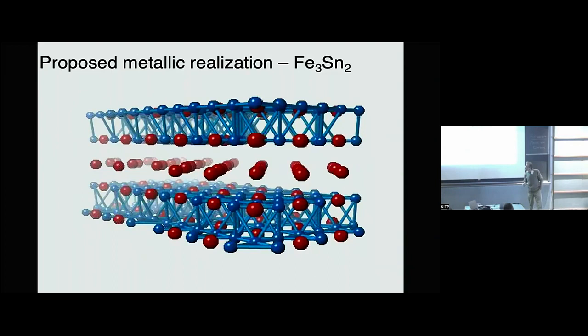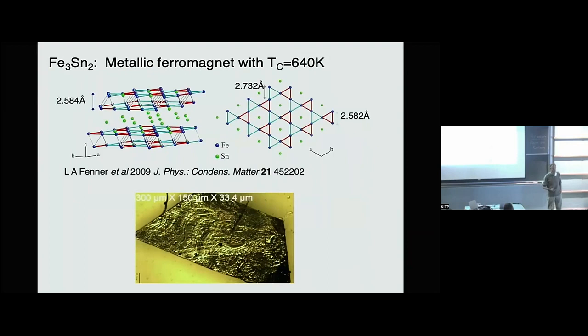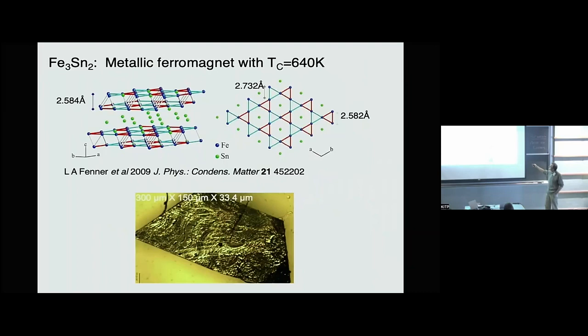That gets us to the material we're looking at: iron 3Sn2. This is a bilayer Kagome system — that's the basic structural motif. The crystals are really too small to do any kind of neutron scattering to decide what the magnetic Hamiltonian might be. It's not an exact Kagome system in the sense that these are not equilateral triangles — they're actually distorted slightly. This material is a very high-temperature ferromagnet with a Curie point of around 600 Kelvin, but has the curiosity that at around 150 Kelvin it has a spin reorientation transition where the spins start out lying perpendicular to the basal planes and then rotate around.